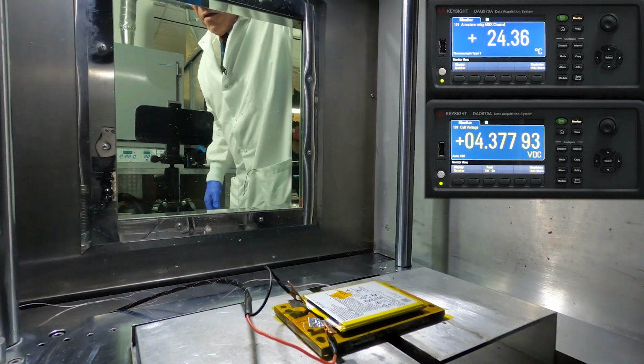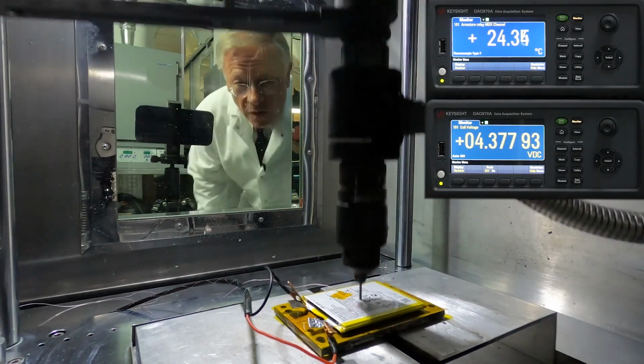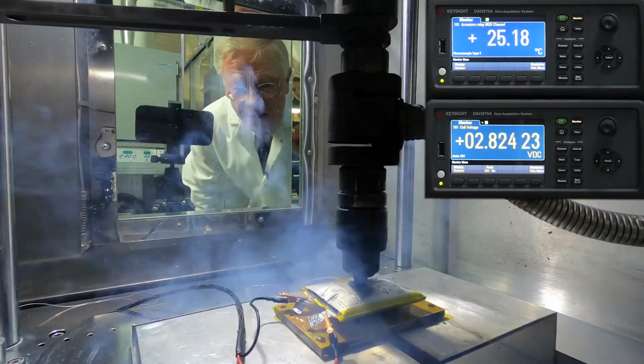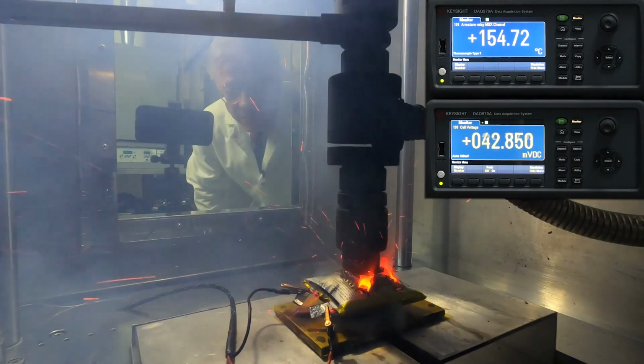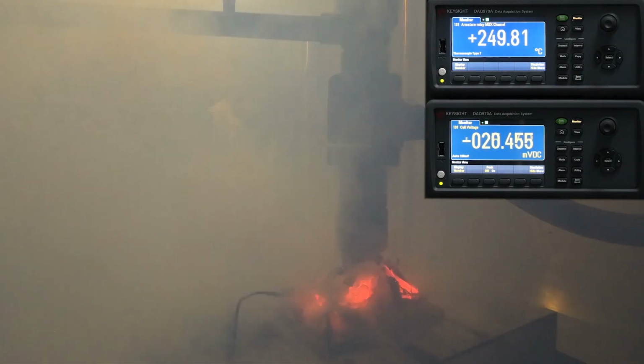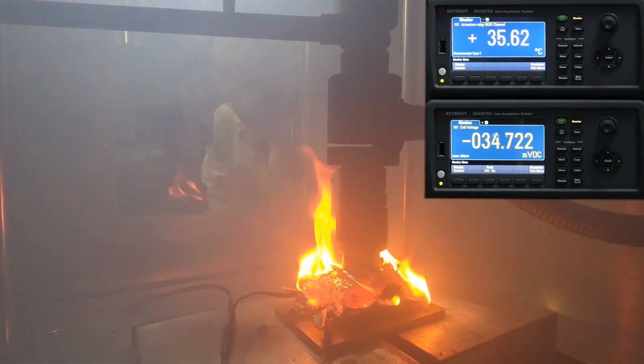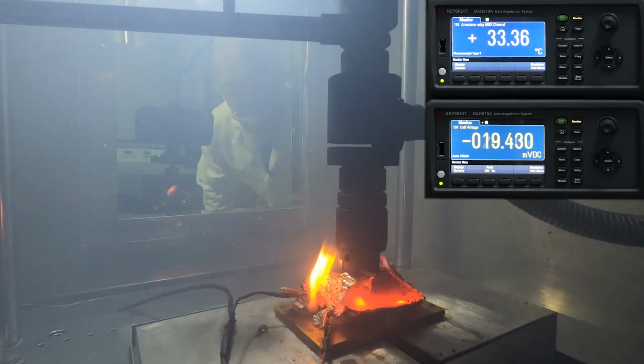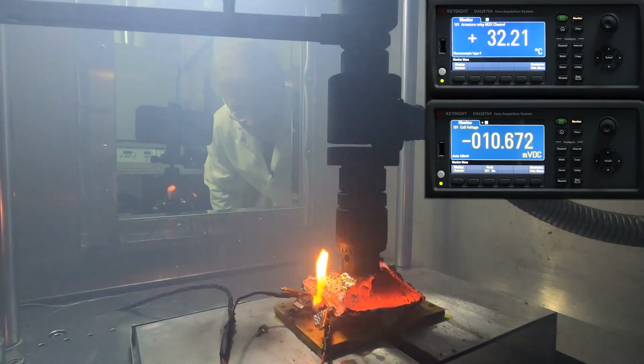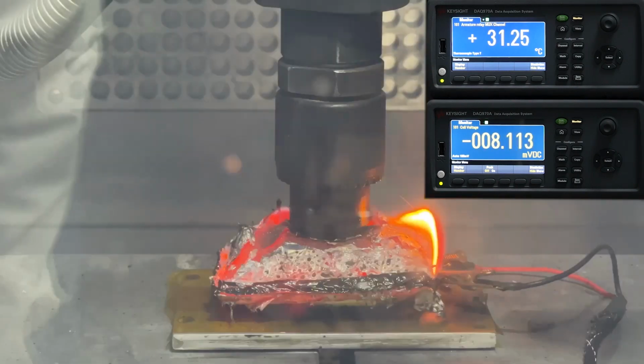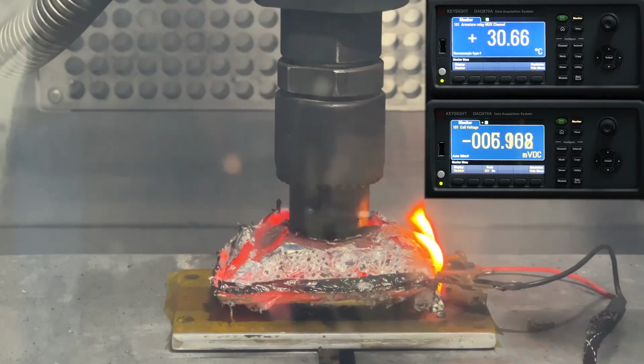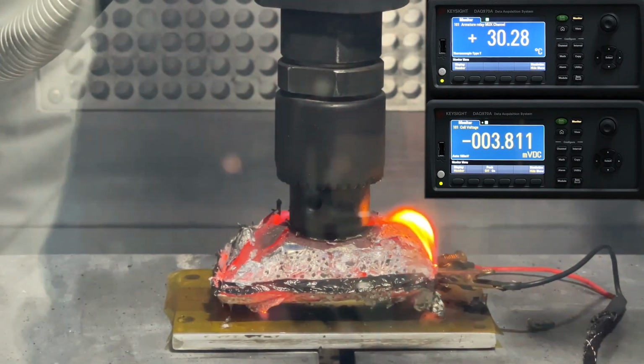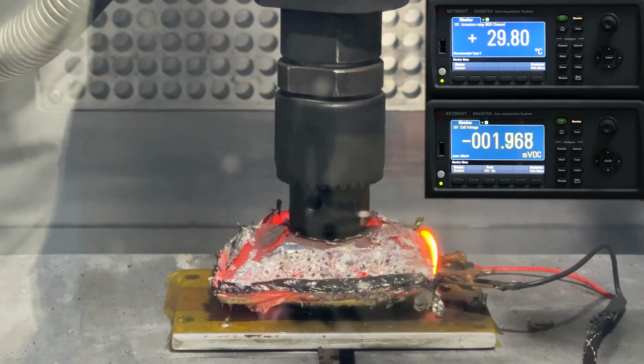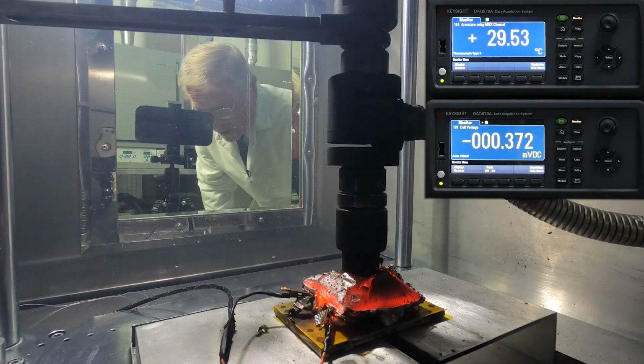And here we go. Okay, you got smoke. It's already opening up. Sparks coming out, bright red, so that you're looking at 800-900 degrees centigrade. Now it's on fire. That is a fire coming from the disintegration of the cathode material, oxidizing anything burnable, but primarily the lithium in the cell. You can see on the left side the thing is red hot,